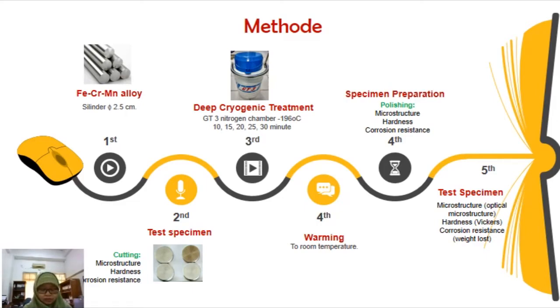Microstructure testing was performed using an Olympus metallurgical system optical microscope with a magnification of 200 times. Hardness testing used a micro hardness tester using the Vickers hardness method with a load of 30 kilograms. Corrosion testing was carried out using the weight loss method in 3.5% NaCl medium.